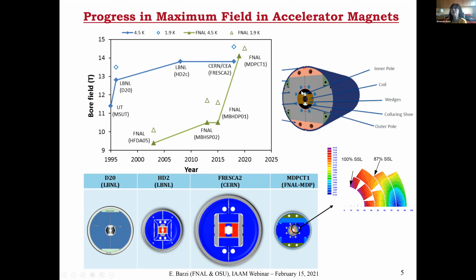But then you can see that these magnets are very complex, because they produce huge Lorentz forces due to the large currents and large fields. And so you need a very, very strong mechanical structure around. Plus, all of these operate at helium temperature, so you have a lot of differential thermal contraction loads, and it's very complex. Anyway, this is just to give you an idea.